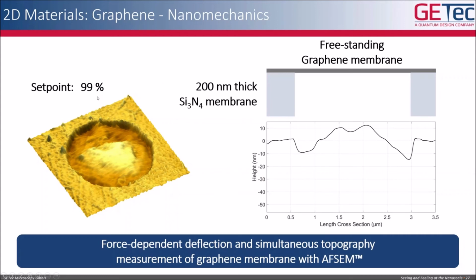If you work at this set point of 99%, you can of course take a line scan across this graphene membrane. What we then did was decrease the set point, therefore increasing the interaction force between the tip and the freestanding graphene membrane.